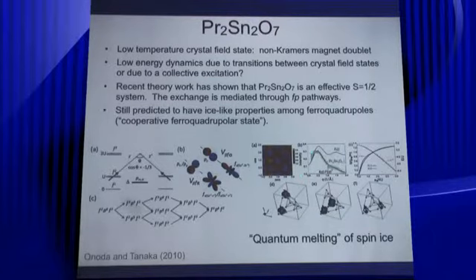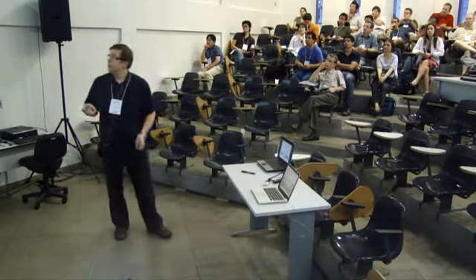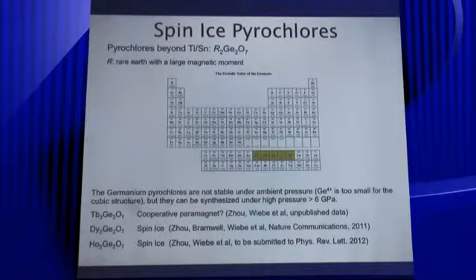And they actually modeled our inelastic data, and they got a better fit than us from looking at their interpretation. So in their interpretation, the quadrupolar component is important towards this order. So we have ice-like properties among ferroquadrupoles at low temperature. So it's a cooperative ferroquadrupolar state, if you'd like. So they called this paper quantum melting of spin ice. So praseodymium stannate isn't a traditional spin ice, but it may still have interesting properties that are waiting to be explored. Okay, so I want to jump towards the germanates.